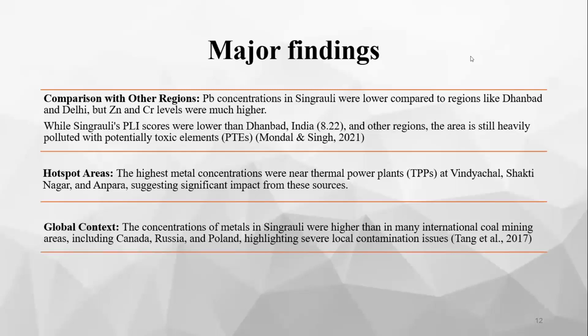Continuing this, the lead concentrations in Singrauli were lower compared to regions like Dhanbad and Delhi, but zinc and chromium levels were much higher. While the Singrauli pollution load index score was lower than Dhanbad, India, which is 8.22 and very high, the area is still heavily polluted with potentially toxic elements. According to the global context, the concentration of metals in Singrauli was higher than in many international coal mining areas, including Canada, Russia, and Poland, highlighting coal contamination issues.